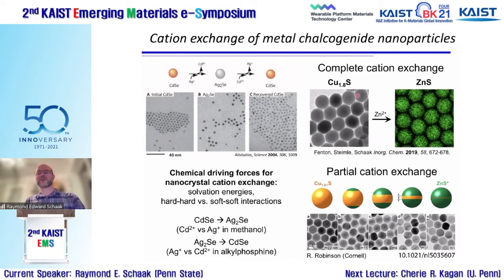And so my group, what you'll see most in this talk, uses copper sulfide as our starting material. And we'll do a series of either complete or partial cation exchanges. What a complete cation exchange would look like is taking this copper sulfide, which has a very unusual formula, Cu1.8S, although we know a little bit more about the chemistry that happens in these reactions. And depending on the system, depending on the chemistry, this actually converts before the cation exchange reaction into something more stoichiometric, like a Cu2S type phase. So you can think about it as being more of a Cu2S going to ZnS with a 2 plus cation exchange, kicking out two 1 plus cations and exchanging them with a single 2 plus cation.